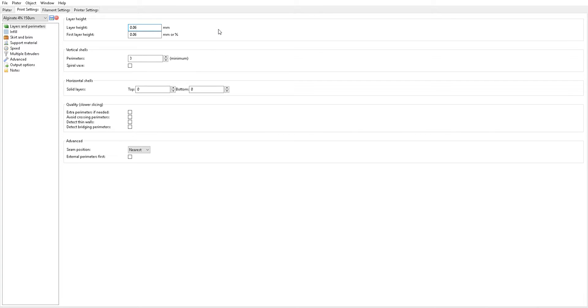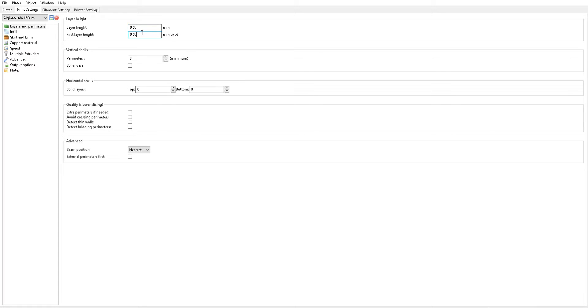So in this case, you'll see that our layer height is 60 micron, which you may think is relatively small in comparison to traditional plastic printers, which normally have an average resolution of 200 microns per layer height. But in this case, we're using 60 microns because the formula that we normally use is that your layer height should be 40% of what your nozzle diameter is or needle diameter. So in this case, we've been using a 150 micron needle and the 60 micron layer height is reflective of that. If we were to switch over to a 250 micron needle, we would have a 100 micron layer height as well. Your first layer height is also just going to be the exact same. No reason to change things here.